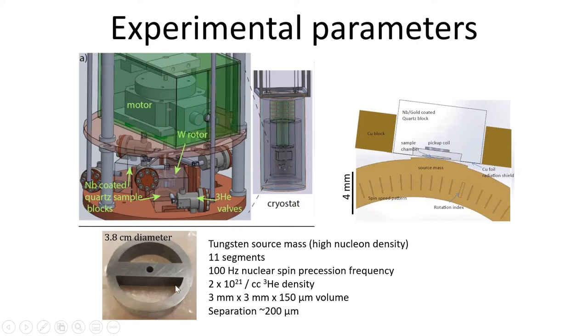Our parameters that we're aiming for in the first round of the experiment: we have this 11 segment tungsten wheel. We have about 100 hertz target frequency for the nuclear Larmor precession frequency. That means that this wheel is actually spinning at 1/11th of that frequency, or around 9 hertz. We have a helium-3 density target of about 2×10^21 at 4K. And then we have a volume for the initial sample chamber of about 3 millimeters by 150 microns, where our mean separation distance is something like 200 microns for this round, in order to look at axions in that kind of milli-eV mass range.